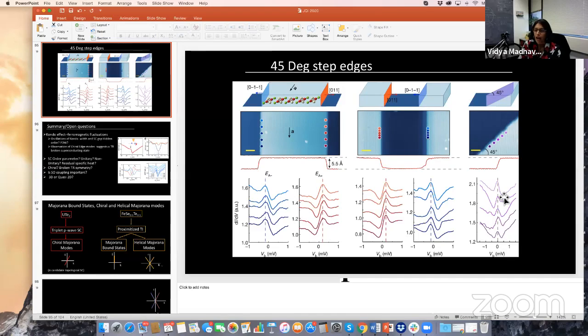So yeah, for iron selenium telluride, you get all kinds of different qualities. The problem is that you can have iron inclusions, so excess iron, and it's an s-wave superconductor, and iron is a magnetic impurity in FeSeTe. So it basically destroys superconductivity. We spent one year looking at samples that had those iron inclusions, and that data was a complete loss. We couldn't publish any of it. So yeah, there's a lot of challenges.